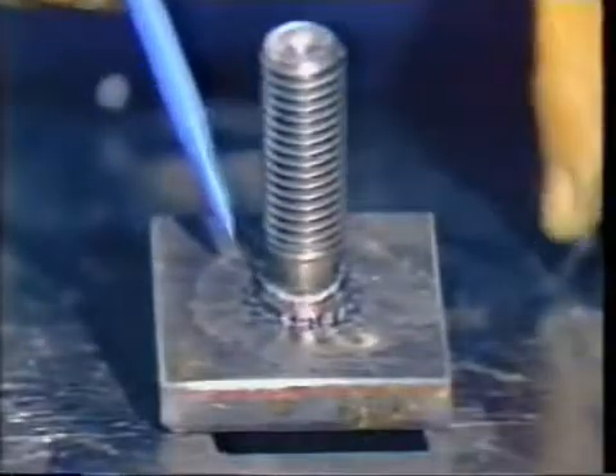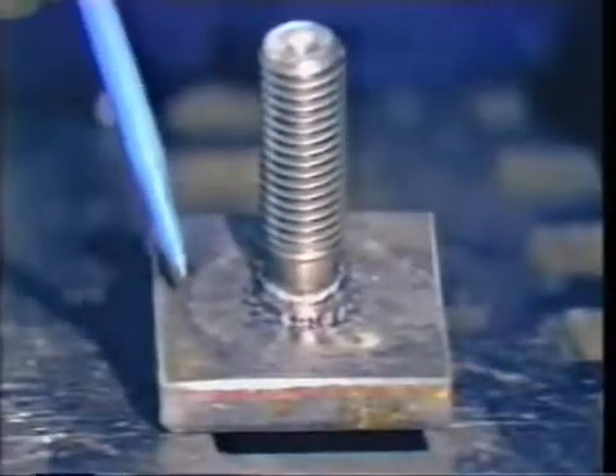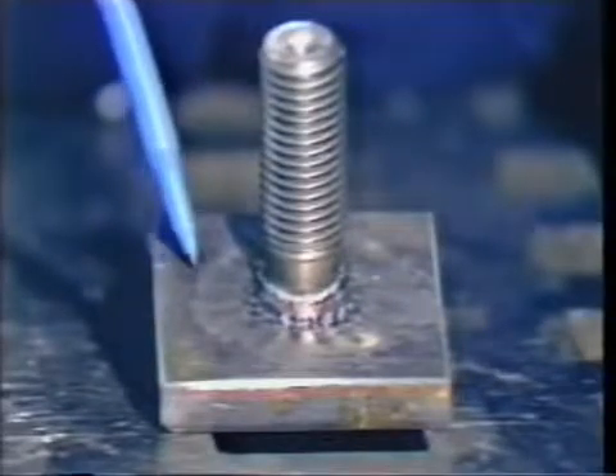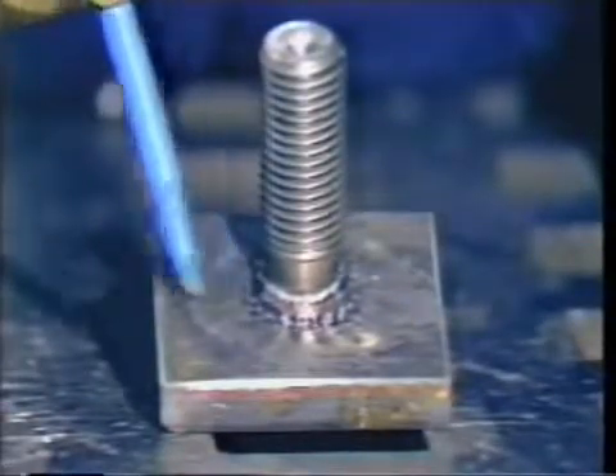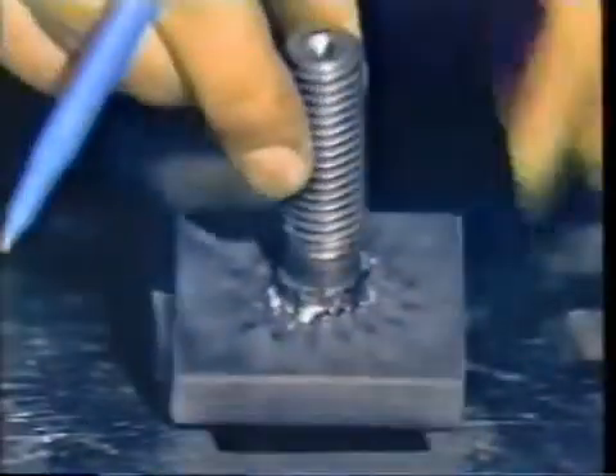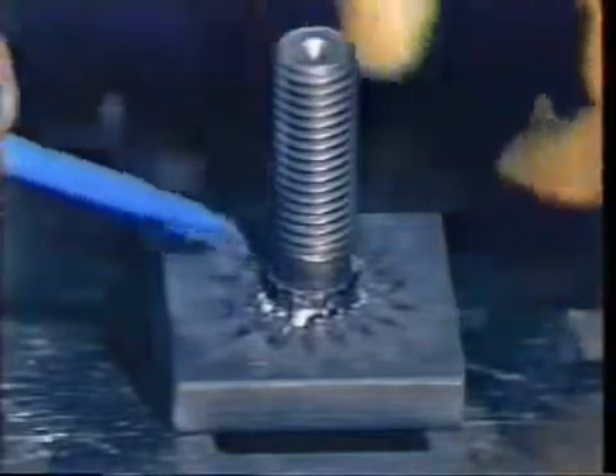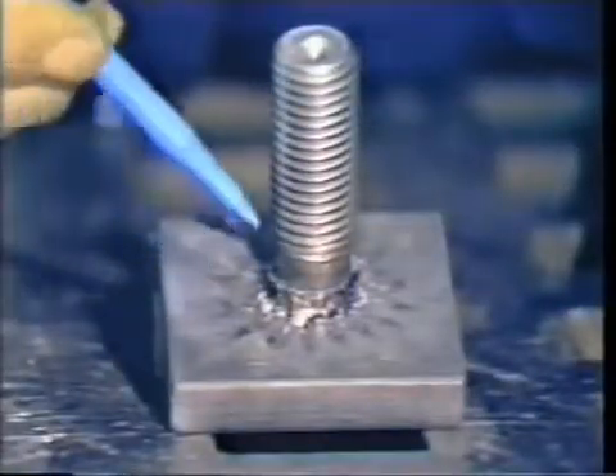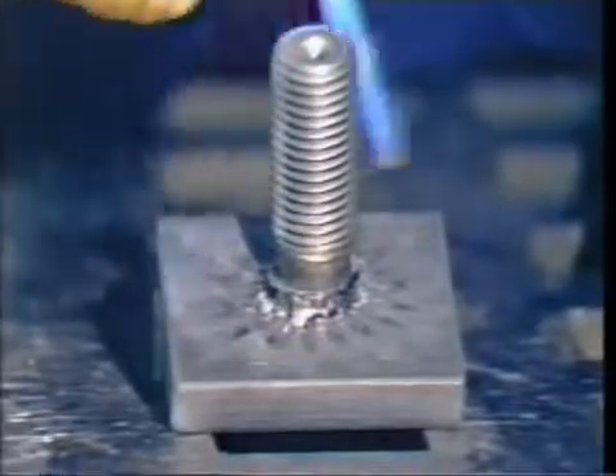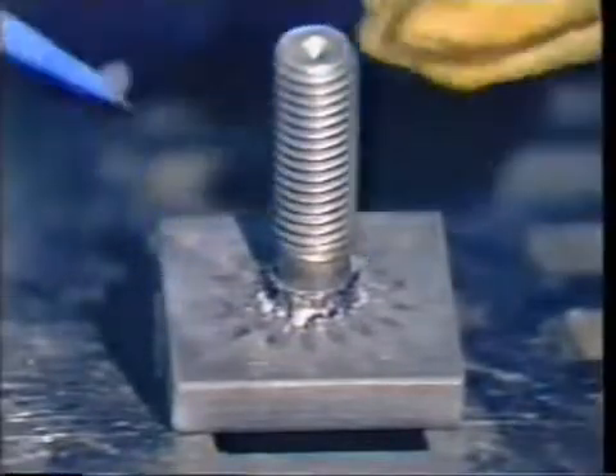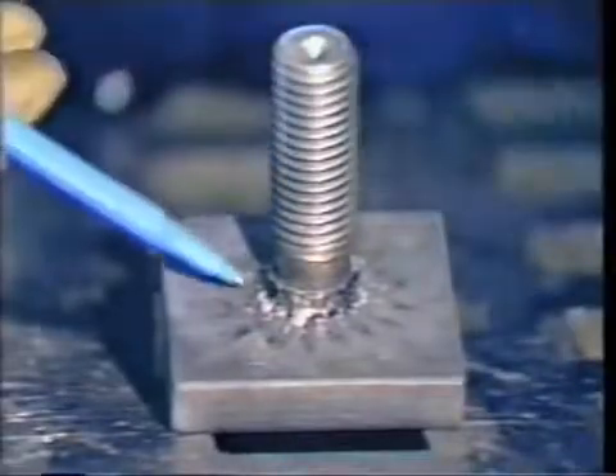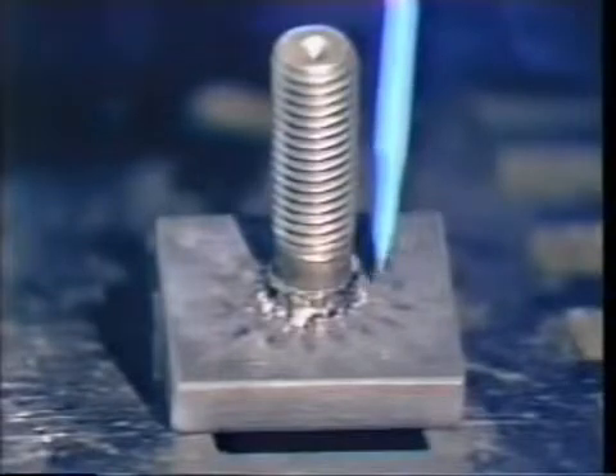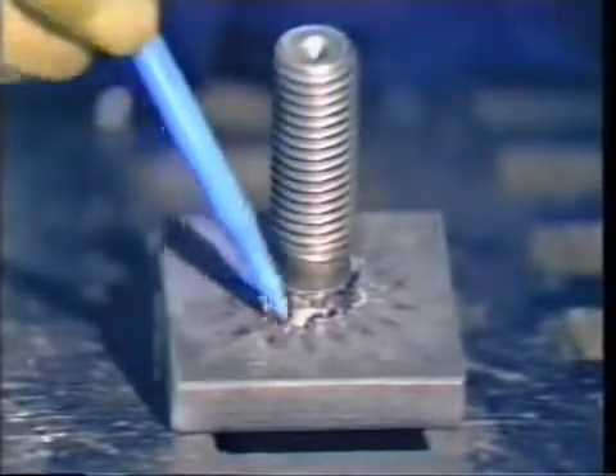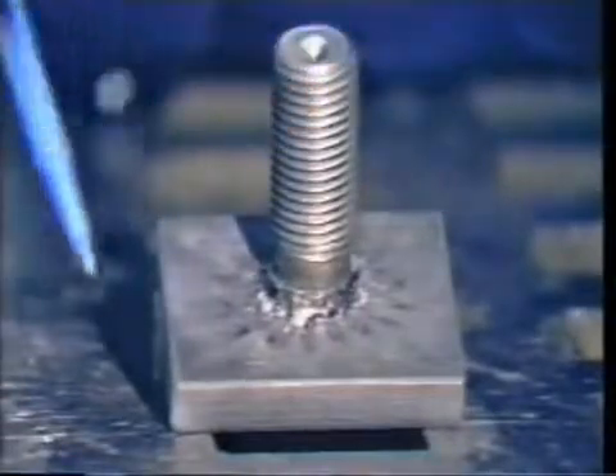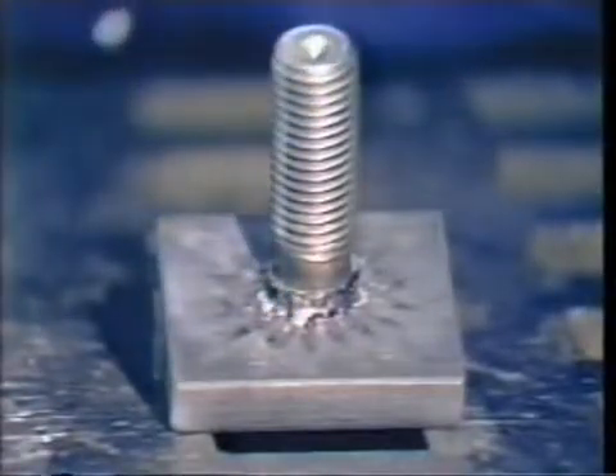The same weld setup onto material that hasn't had the mill scale removed is going to have more slag coming from the vents of the ferrule. This slag material is a product of the mill scale. We had the same burn-off, the same wetting, bonding, but the mill scale acts somewhat as an insulator that keeps the fillet from giving you the bright radius of blend into the base material and adds to the amount of slag coming out the vents of the ferrule. It also traps pieces of the ferrule in the material between the vents.